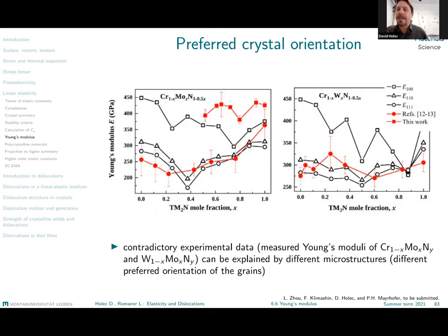This is what is seen in the scatter of this data, where this scatter of the experimental measurements originates from. The lower data set is much better represented by the directional Young's moduli calculated for 111 directions of this material, whereas the upper data set is not perfectly represented, but corresponds much, much better to the directional Young's moduli calculated for 100 direction. And so indeed, the directional dependence of mechanical properties exists. It is there.